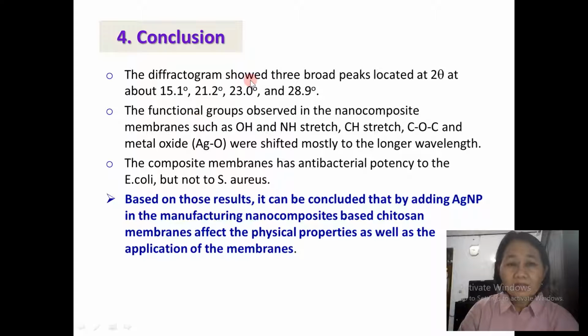The diffractogram showed broad peaks located at 2 theta at about 15.1, 21.2, 23, and 28.9. The functional groups observed in the nanocomposite membrane, such as OH and NH stretch, CH stretch, C-O-C, and metal oxide, were shifted mostly to longer wavelength. The composite membranes have antibacterial potency against E. coli but not against S. aureus.